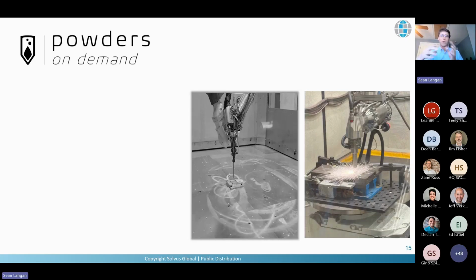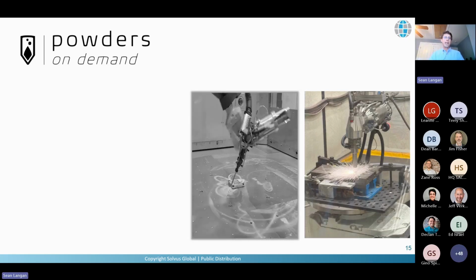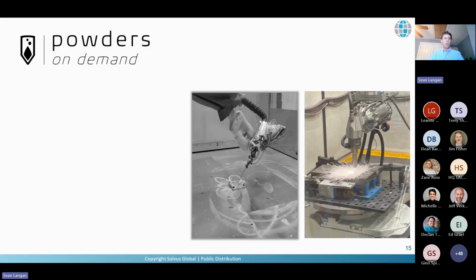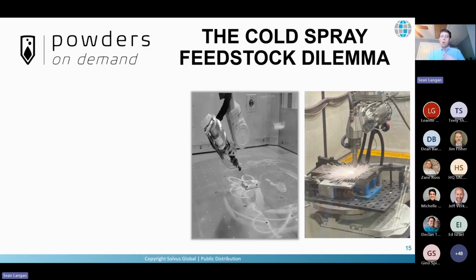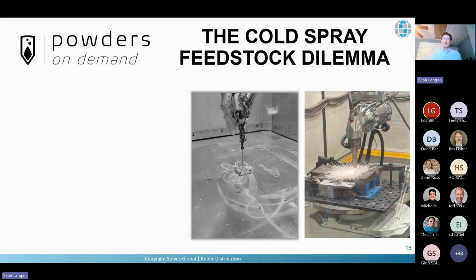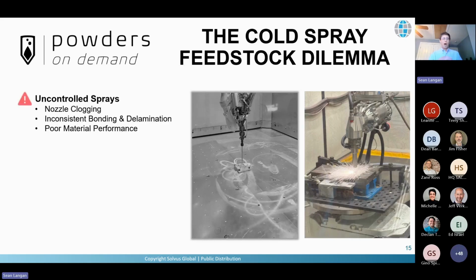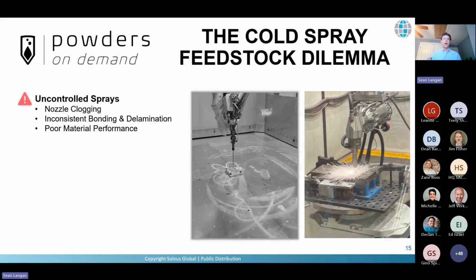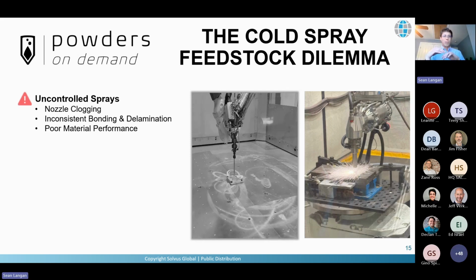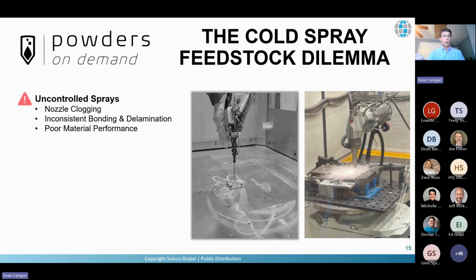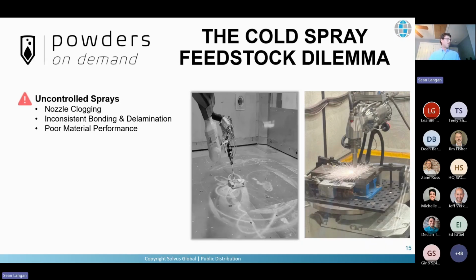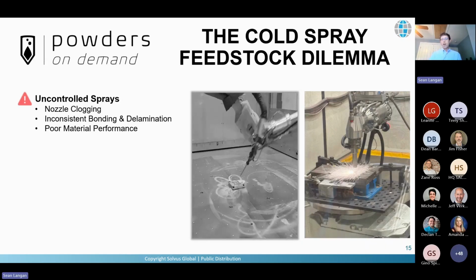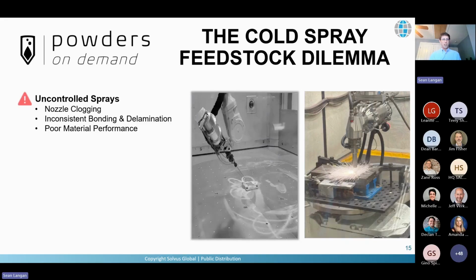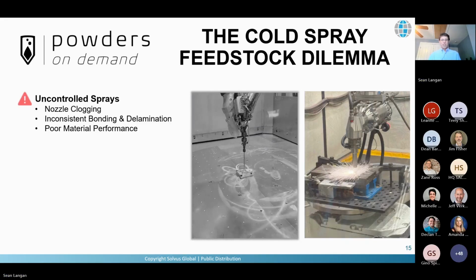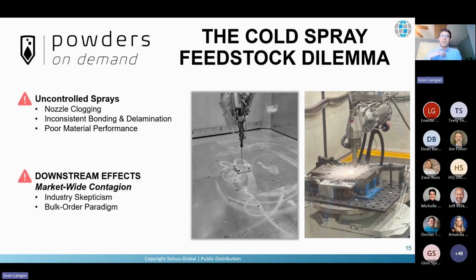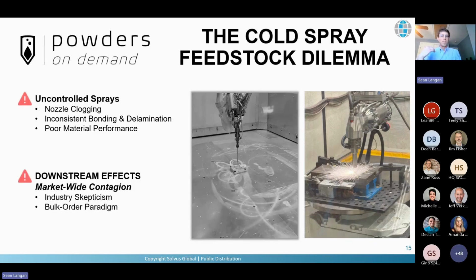In the early days of cold spray, people were really excited about the technology. The problem was when they went to their local atomizer, bought powder, and threw it in the system, they didn't get the results that they were looking for. They often found nozzle clogging. That's where the powder is deposited in the nozzle that they're being sprayed through as opposed to on the substrate where they're supposed to deposit, and poor material performance from things like inconsistent bonding and delamination, porosity, low mechanical properties, etc. This led to a lot of people not trusting the new technology despite its promising features.